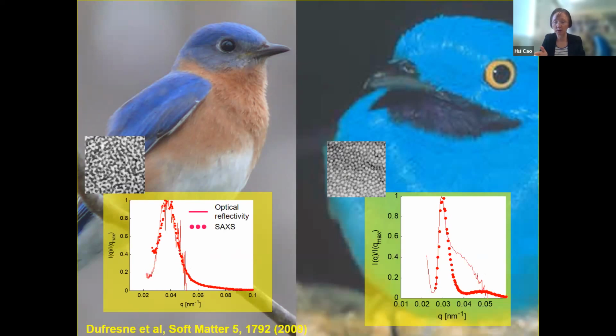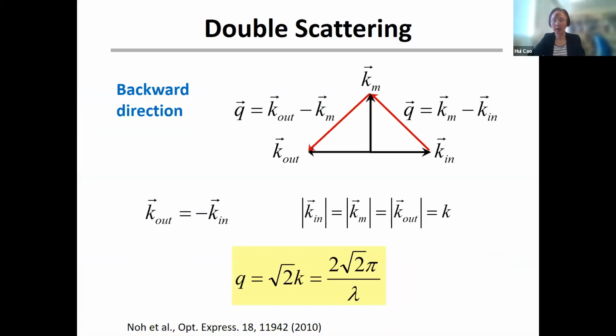So that is confirmed. This optical reflection peak is coming from a structure that has some particular spatial frequencies, which is given to us by the small angle X-ray scattering. This looks great for the channel type on the left, but for the sphere type, when we put them on top of each other, we see the main peak of the optical reflection spectrum matches well with the X-ray scattering peak. But there's a shoulder here. Where does that come from? That comes from double scattering. That means the light is scattered twice by the structure: the first time from the wave vector K in to an intermediate vector Km, and then scattered again from Km to the final vector K out.